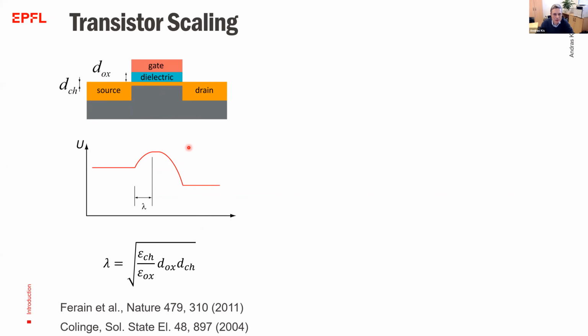So in order to make a transistor that you can efficiently switch off, if you want to scale the length, you also have to scale the thickness. And this is where using 2D materials, such as, for example, molybdenum disulfide, becomes a very good choice eventually, because it allows you to shrink this critical length for making a transistor by just taking a thinner material.